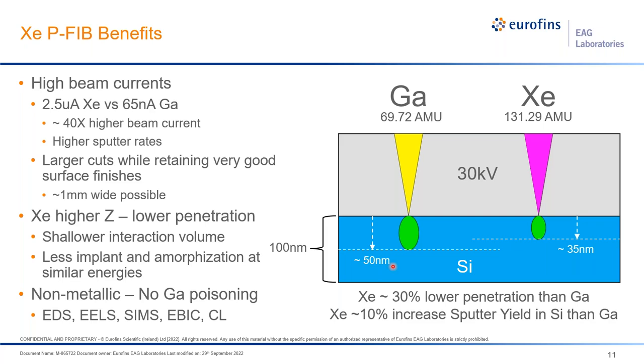Secondly, xenon has a higher atomic mass than gallium, so that's going to produce approximately a 10% increase in the sputter yield over gallium, especially in the case of silicon, as well as decreasing the penetration depth by about 30%. And so this is going to reduce the implantation and amorphization of the sample as compared to gallium FIB, which improves the surface sensitivity of subsequent analyses, whether in SEM or STEM.